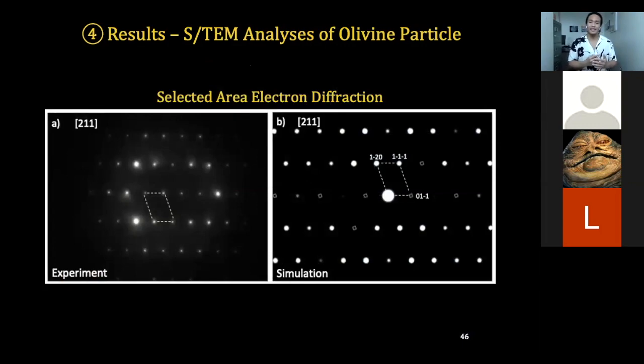On your screen is a selected area electron diffraction, which we were also able to do. This gives us patterns where we can look for the crystal structure of our sample. To the left is the electron diffraction pattern that we got during the experiment for our actual sample, and this was along the 211 zone axis. This is then compared to a simulation that was done using the CrystalMaker software of an olivine particle along the 211 zone axis. Looking at the patterns, both the geometries of the patterns as well as the d-spacings, or the spacings between the individual dots, are a match. And so essentially, this is an additional confirmation that our particle is indeed an olivine.